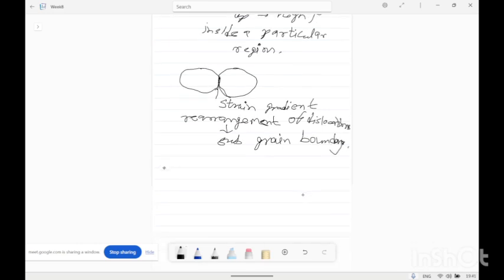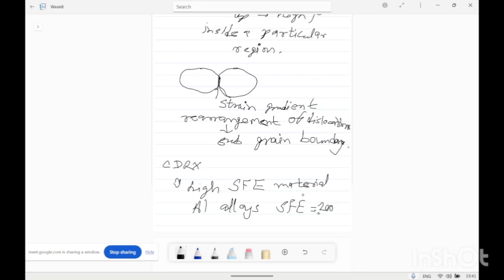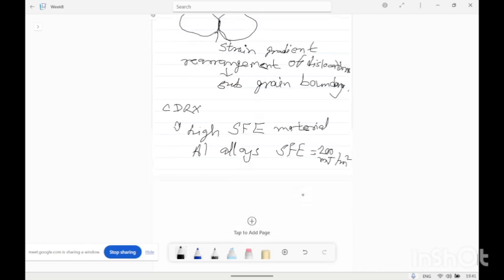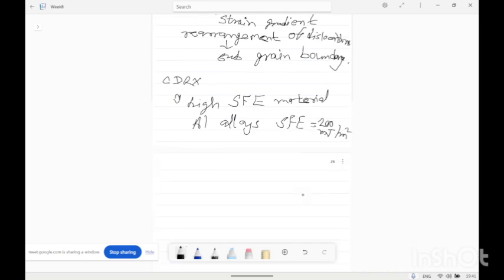While in the continuous dynamic recrystallization that happens in high stacking fault energy materials like aluminium alloys, which has a stacking fault energy of 200 millijoules per meter square, that leads to the rearrangement of dislocations near the subgrain boundaries, leading to the formation of high angle and low angle grain boundaries.